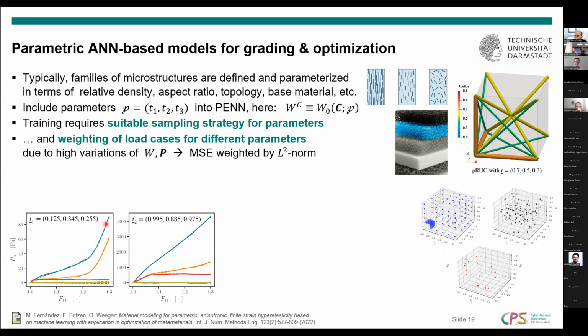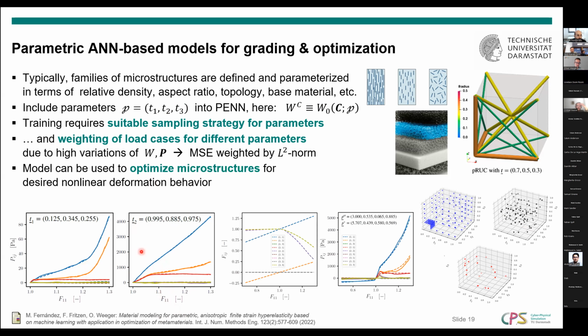So for that, it's very important that you introduce a proper weighting into these different cases that you're trying to approximate. And we found here that a very good solution is basically to compute the L2 norm, or a discrete approximation of the L2 norm, of these stresses integrated over the whole deformation range. And then you weigh by these L2 norms. And then when we do that, we get a very good fit. So these curves show the data in dashed lines and the model prediction of our parameterized model in continuous lines, and you can hardly distinguish them, even though they have very different scales.